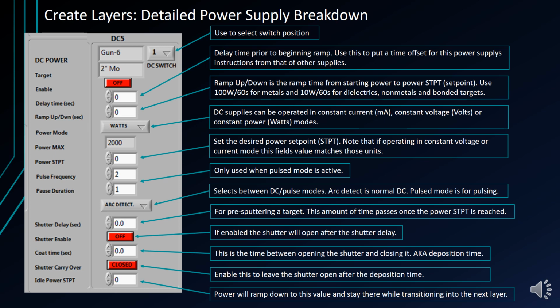Once the power set point is reached, it will count through the shutter delay time. This is typically used to perform a pre-sputter prior to opening the shutter. If the shutter enable is on, then the shutter will open at the end of the shutter delay. It will then count through the coat time. If shutter carryover is set to closed, then the shutter will close at the end of the coating time. If not, the shutter will remain open as the process transitions into the next layer.